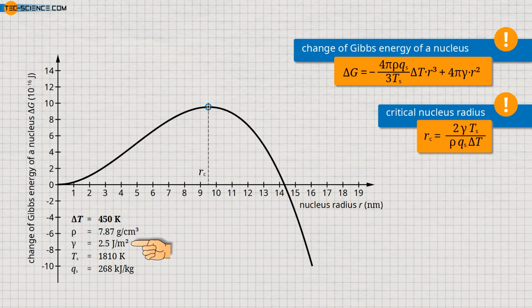If one assumes a surface tension of 2.5 joules per square meter, a specific heat of solidification of 268 kilojoules per kilogram and a density of 7.87 grams per cubic centimeter, the above-mentioned supercooling of 450 Kelvin results in a critical nucleus radius of about 9.5 nanometers. About 300,000 atoms are then required for the formation of such a nucleus. It should be noted at this point that the relatively high supercooling of 450 Kelvin applies only to homogeneous nucleation. Heterogeneous nucleation, on the other hand, requires only a fraction of this supercooling, so that homogeneous nucleation in molten metals is rather unlikely. In another video, heterogeneous nucleation is explained in more detail.